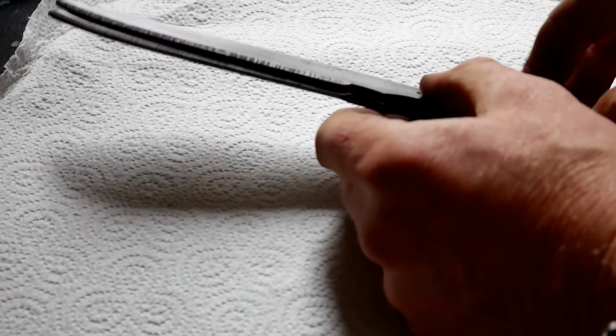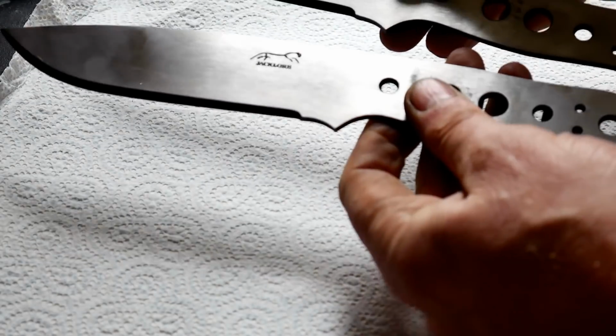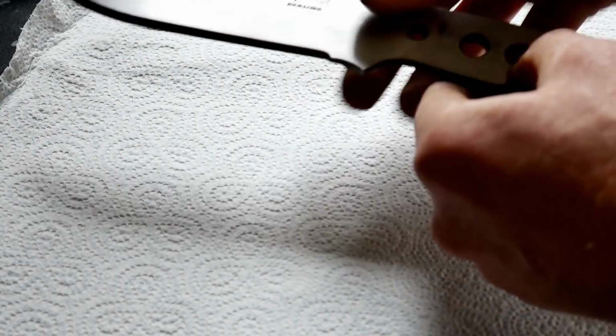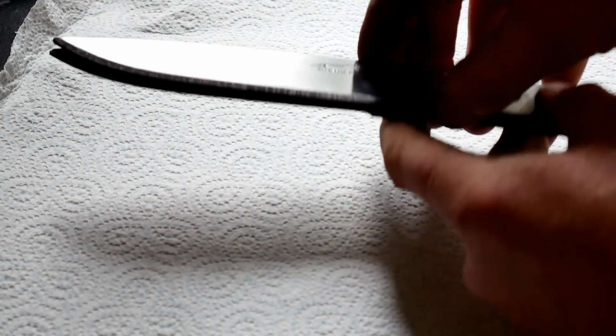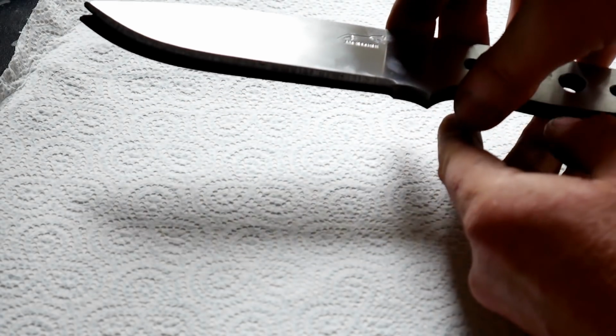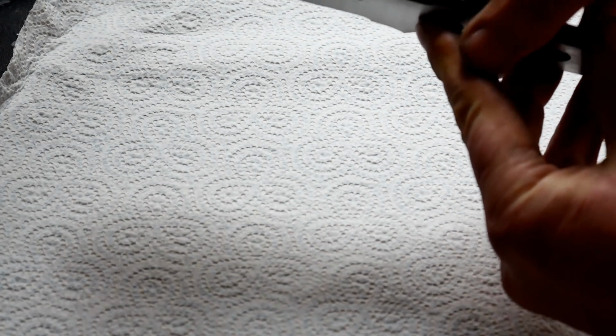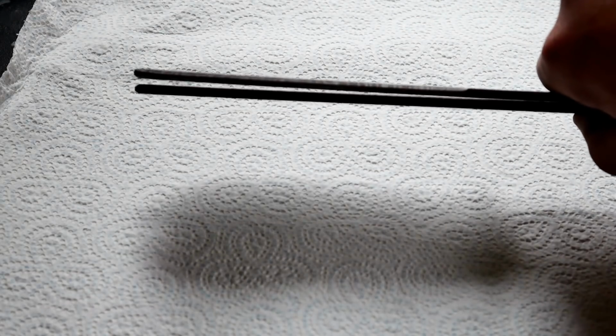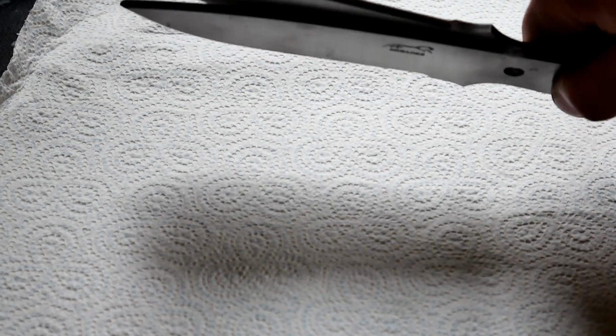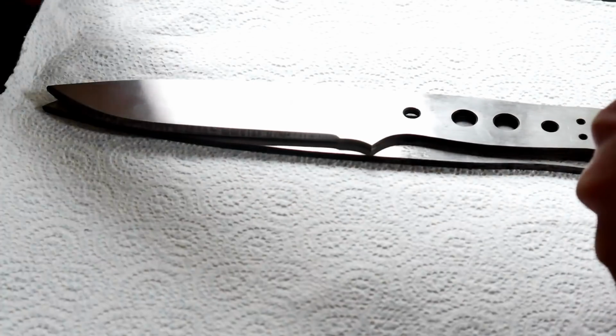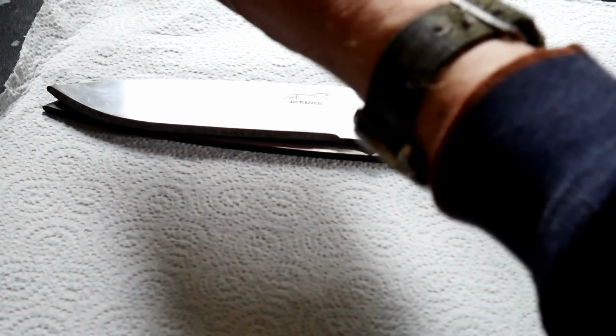When you look at the blades in the same orientation, in other words both like that, they look quite flat when you put them together, but they both warp the same way. In fact, most knives will warp a little bit in heat treat, and if you put them the other way round, then you'll be able to see that warp. It's quite marked. So what I do now, I stack all my blades counter warp to each other. And these have all been stacked counter warped,